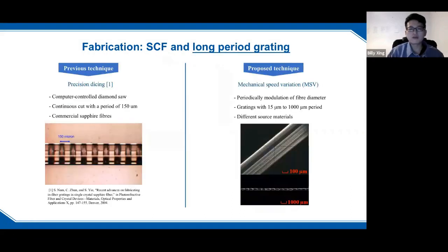So how do we fabricate the long period grating? Because sapphire fiber, or single crystal fiber, is a very hard material with a very high melting point, conventional fabrication for long period gratings cannot be applied to single crystal fiber. So this always remains a challenge. The previous technique for long period gratings on single crystal fiber is precision dicing, where you use a computer controlled diamond saw to continuously cut gratings with a period of 150 micron. This was done on commercial sapphire fibers.